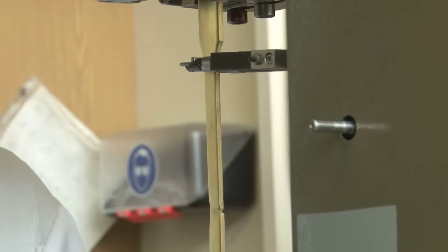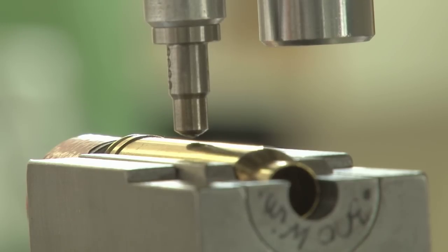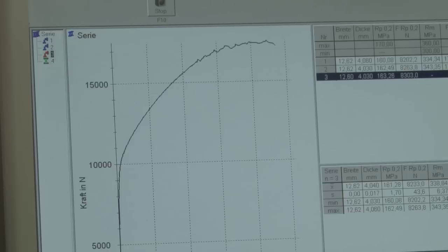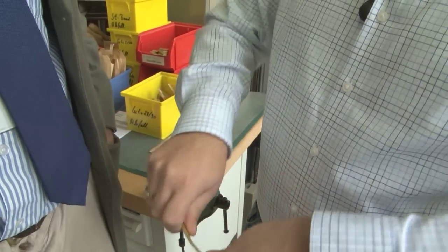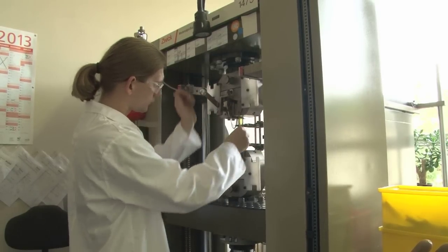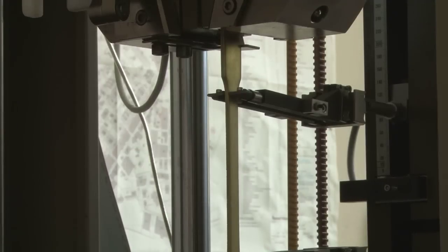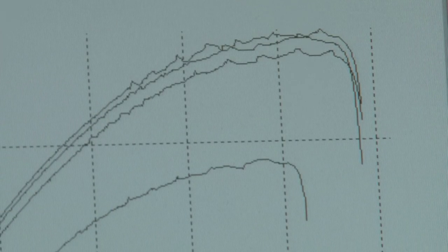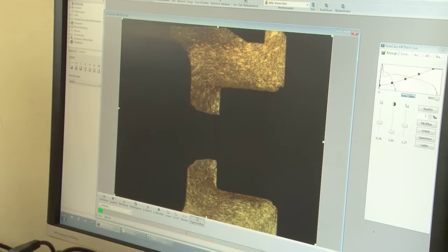RWS stress-tests all metals that make it to the site — there needs to be consistency. The bullet casing is far from uniform: flexible at the neck, strong at the primer seat, and the bullet is stress-tested every five millimetres. We are looking for tensile strength and elongation of the material, testing that all incoming material has the right parameters. This material is very soft, but when I work it like this I get hardening in it, and the hardened material isn't right — that creates a different graph and a big impact on the performance of bullets leaving the factory.